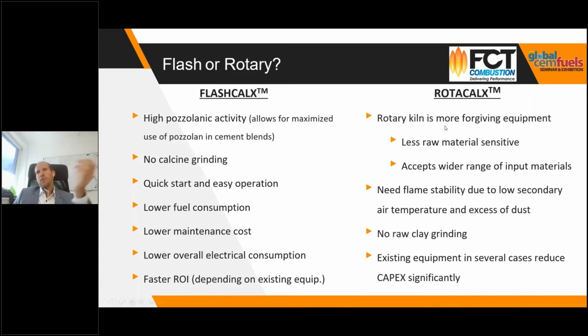Obviously, the rotary kiln has also its advantages, so it's more forgiving, it's less sensitive in terms of which type of raw material you can use. As I mentioned, you can use larger moisture, you can use larger particle sizes, and so on. The secondary air temperatures are much lower than in a clinker kiln, so it's harder for you to use higher amounts of alternative fuel, while in the flash calciner, you produce the gases in a separate hot gas generator, and there you can control the combustion much better.